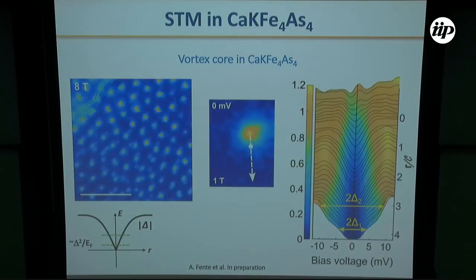When we look at the evolution of the superconducting density of states when going from inside to outside the vortex core, we find the presence of a localized state at a positive bias at the center of the vortex core that evolves to the two-gap structure that we observe outside the vortex. As we know, the lowest energy localized state appears at the energy of delta squared over the Fermi energy. In a conventional superconductor, this value is too small, it's practically 0.